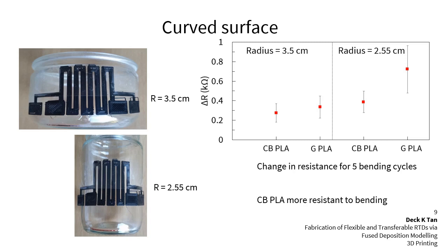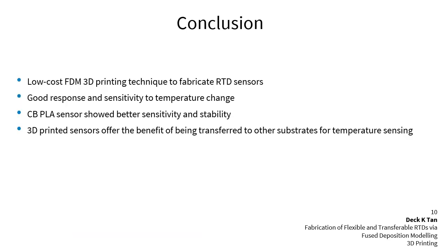The estimated strain on a smaller radius is larger than on the larger radius, of course. Hence the change in resistance also increased when the sensors were bent over the smaller radius curved surface. Nevertheless, the carbon black PLA sensors showed better stability and resistance to bending as the change is smaller than the graphene PLA sensor. So in conclusion, for this simple study